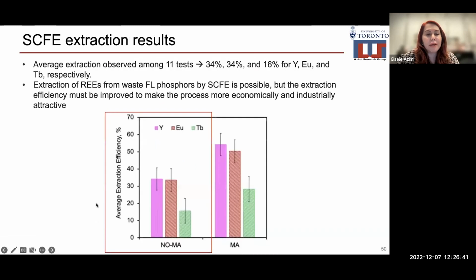We performed supercritical fluid extraction using the DOE matrix. We had 11 tests, and we observed a 34% extraction for yttrium and europium and 16% for terbium. So in this case, we showed the feasibility of recovering rare earth elements from these fluorescent lamp phosphors using SCFE, but the extractions were low, so we needed to improve them to make the process economically and industrially attractive.